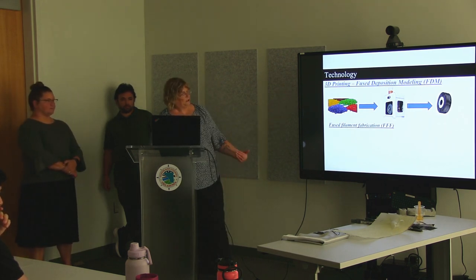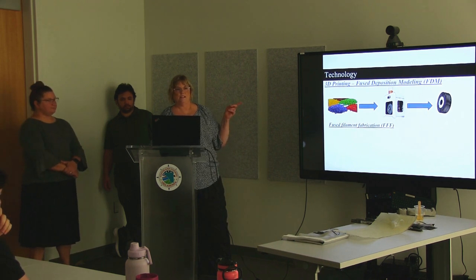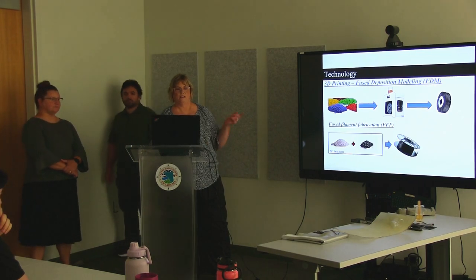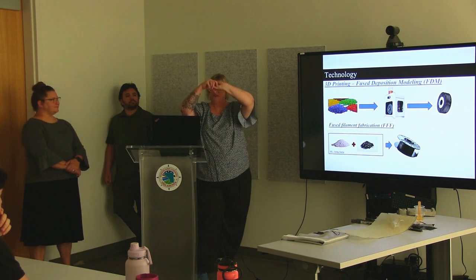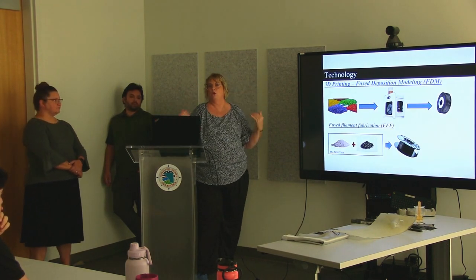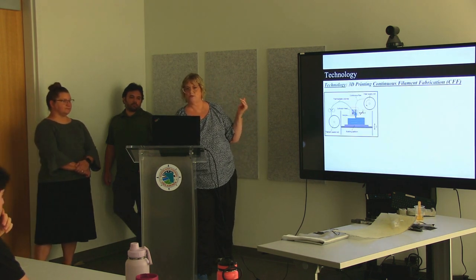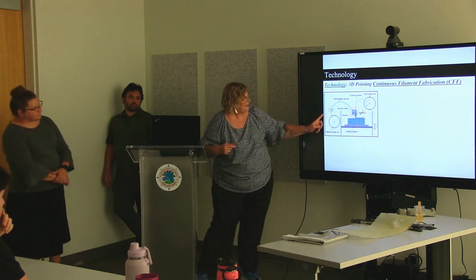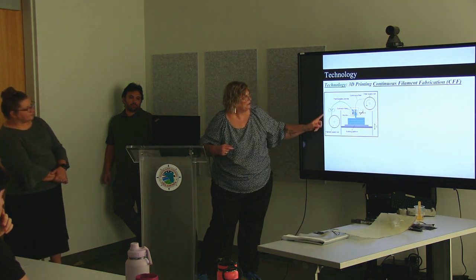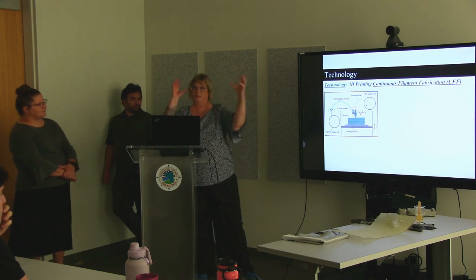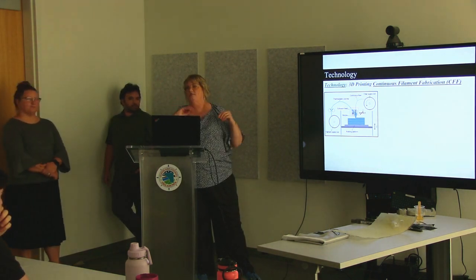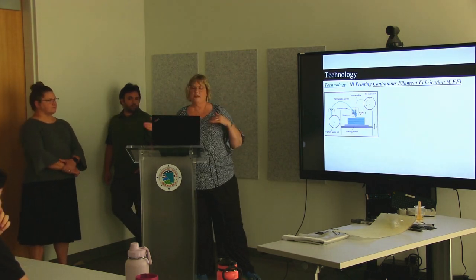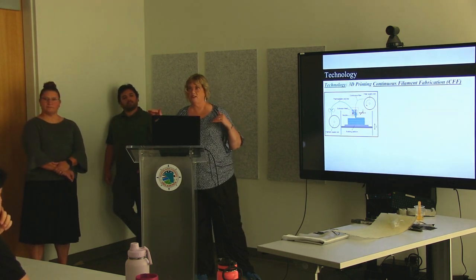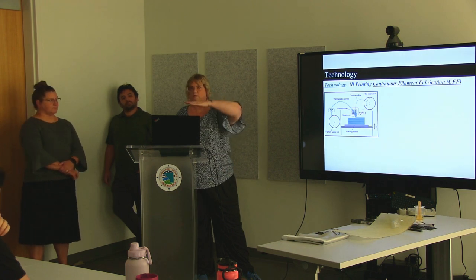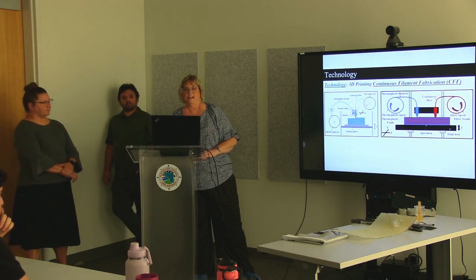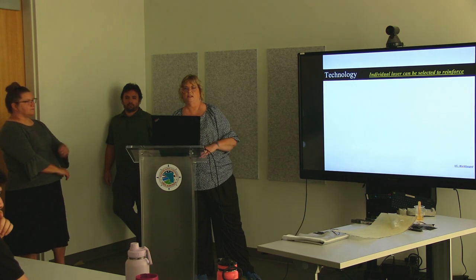3D printing is fairly new to the game in this. With 3D printing, they can do fused modeling where the 3D printer would melt the fibers and the plastic together and run them through, or you can have it separate, which is what the 3D printer we used, where, if you can see here, we had a thermoplastic polymer and a continuous fiber on two different spools that have two different nozzles on the printer. And then for every 1/10 of a millimeter layer, we could tell it whether it was doing the nylon between the layers or doing the glass fiber, and at what specific angle it should print it. And that kind of shows you how it would wind through the two separate nozzles.